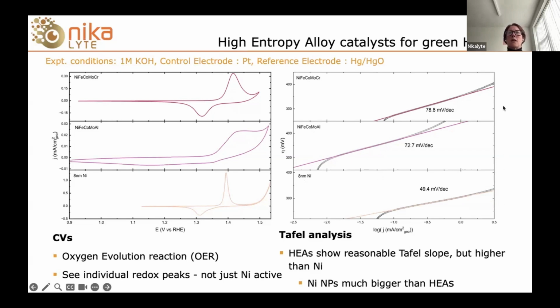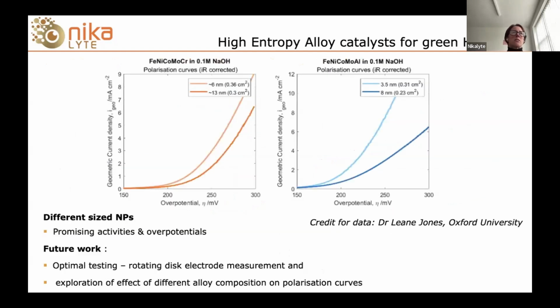But in any case, what we were pleased to see here is that the Tafel slope here, this millivolts per decade, is actually not so different to nickel. And we're quite encouraged by that as a first result. And certainly we're going to go back and look at optimizing these materials further, and also optimizing the experiments to take account for things like the difference in size of the nanoparticles. We also looked at the polarization curves for the two different alloys. So in this case, we've just got the nickel iron moly cobalt chrome and the nickel iron moly cobalt aluminium.